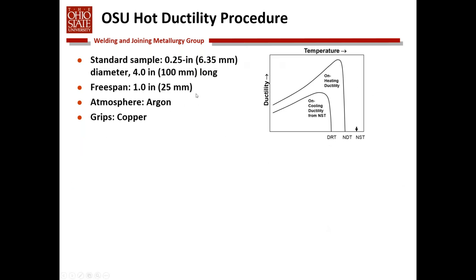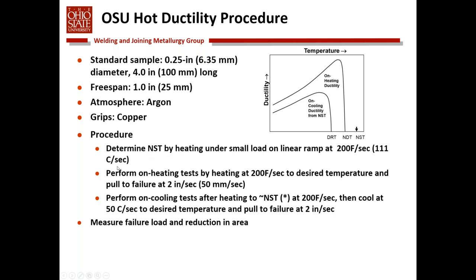So the procedure used here uses a quarter inch diameter, 4 inch long sample. We use a 1 inch free span. We typically run our tests in argon, and we use copper grips. We determine the nil strength temperature by heating under a very small load, typically 10 kilograms or less. And we simply run the sample up on a linear ramp and wait till it comes apart. And we normally run a couple of those, two or three maybe, to get good statistics on what the temperature is, where there's sufficient liquid that the material has no strength.